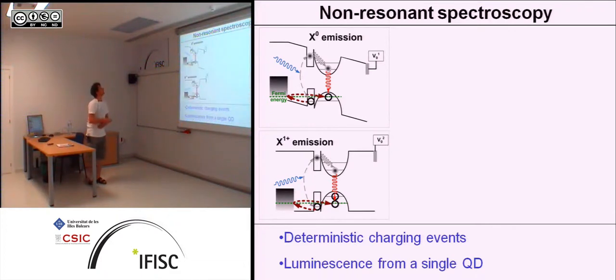Okay, so how now do we use all this structure in the experimental setup? Well, so here again we see the band structure of the device for different gate biases, gate voltages. So for the first one, the ground state of the valence band minimum is in contact here with a p-doped back contact. That means that that'll be occupied by one hole. If we now excite the exciton with a higher energy laser, this exciton will provide one electron which relaxes into the quantum dot, usually with phonon interaction, and this can now relax and recombine with the hole in the valence band.